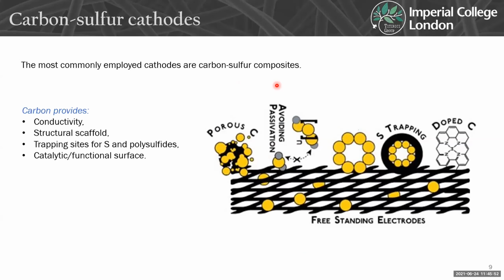Often one of the most common approaches is porous carbons that encapsulate the sulfur species and the polysulfide species, so physical encapsulation. But you can also have chemical trapping as well, where you have functionalized surfaces that can trap the sulfur and the polysulfide species to prevent any shuttling away from the cathode. And then there's also the potential to add catalytic elements into the carbon framework to try to increase the conversion of the polysulfides at the end.